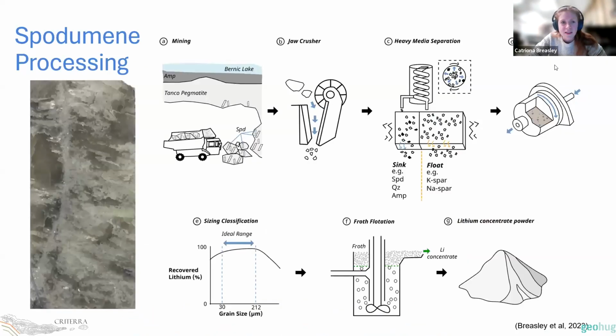So here is the typical spodumene processing cycle. We start off underground at the pegmatite, where you can blast out your material and truck it up to the surface. You then take your rock, put it through a jaw crusher to roughly pebble size, where it can then go through a heavy media separator. And this is essentially a tube that spins round and spits out the rock, and then the table shakes, and this can produce two main piles, your sinks and your floats.